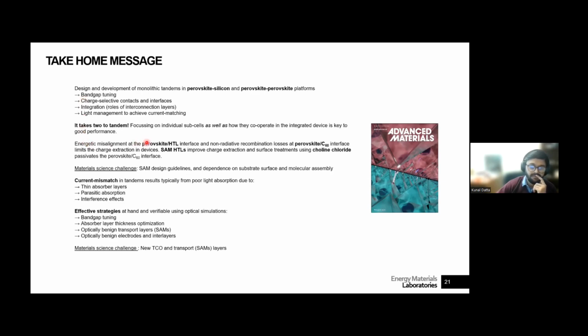We observed that the perovskite HTL interface and the perovskite C60 interface are the sites for primarily a lot of voltage loss. So we optimized it by using SAMs in the case of the HTL, and by using a choline chloride passivation layer in the case of the ETL. But here there's a challenge in my mind, at least, that these SAMs showed up a few years ago, and now the library is growing.